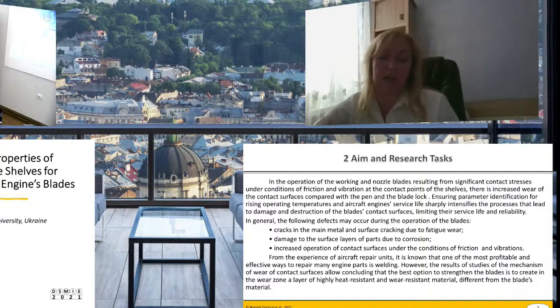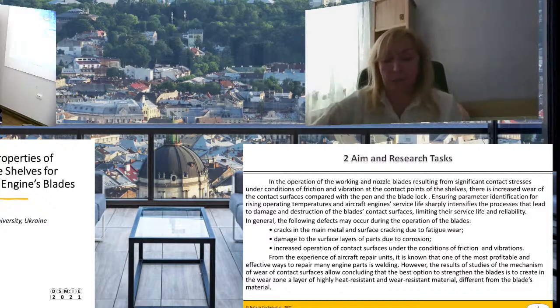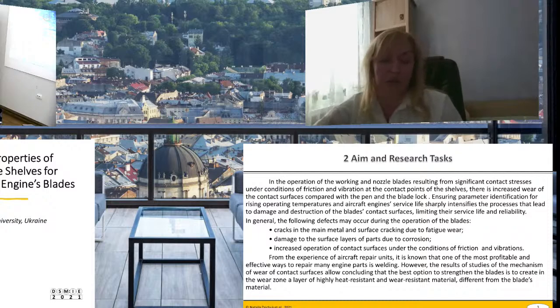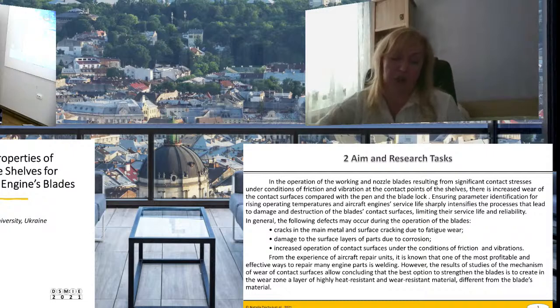In general, the following defects may occur during the operation of the blades: cracks in the base metal and surface cracking due to fatigue, wear, damage to the surface layer of parts due to corrosion, and increased wear of the contact surface under conditions of friction and vibration.